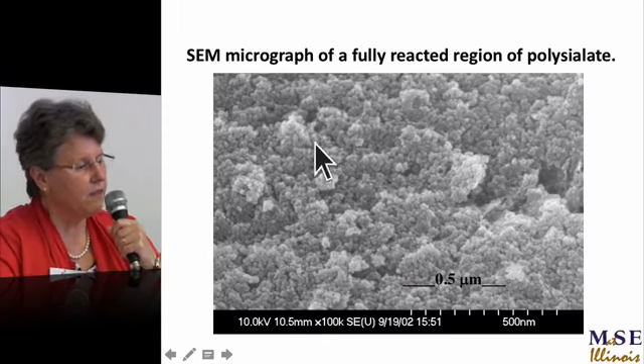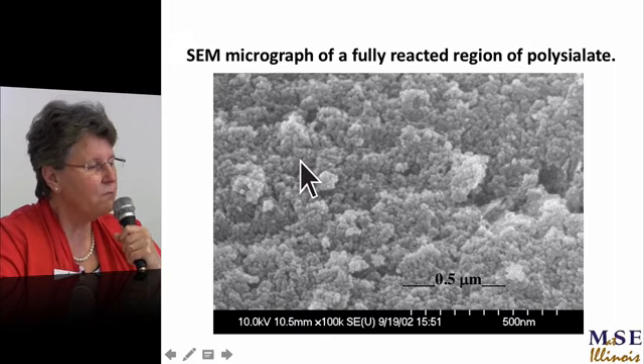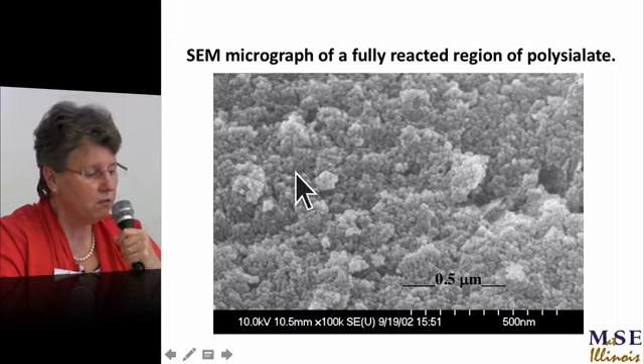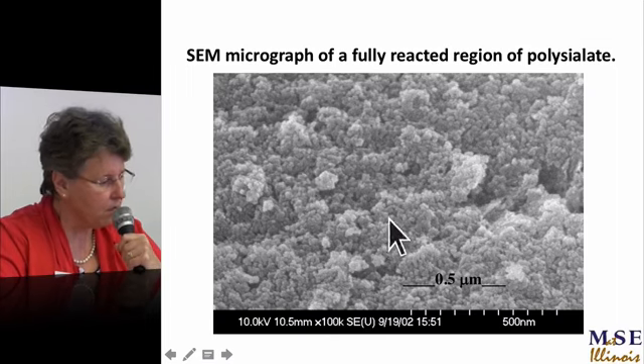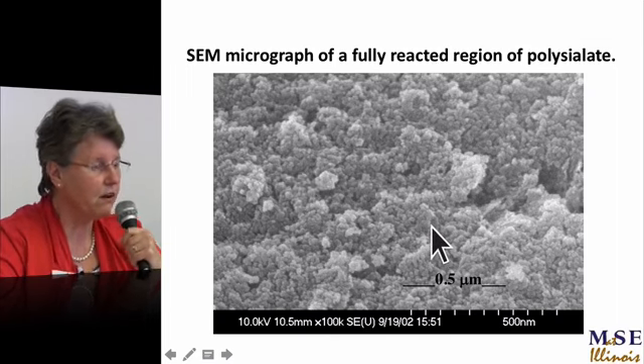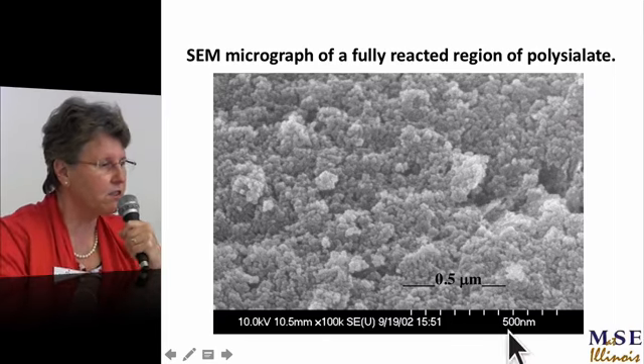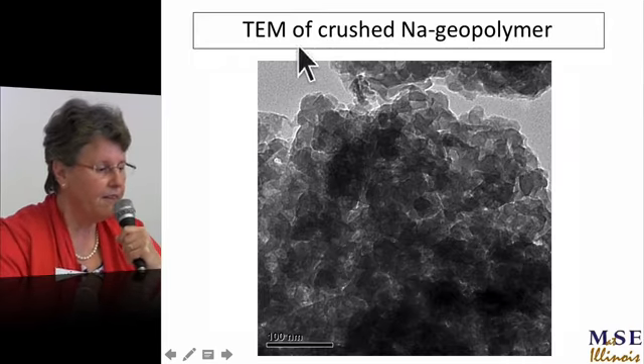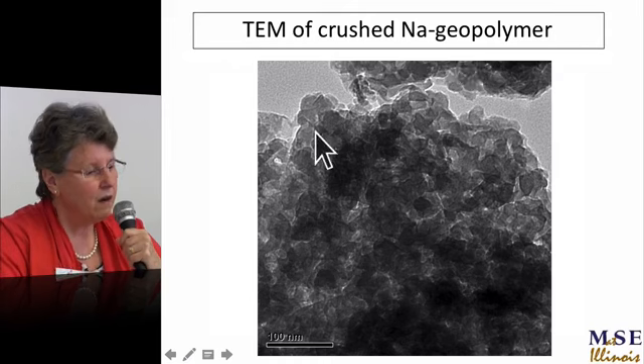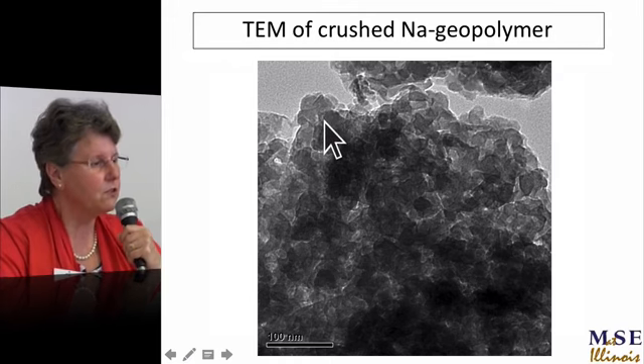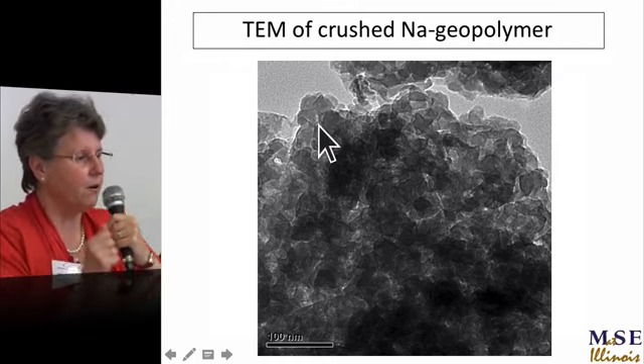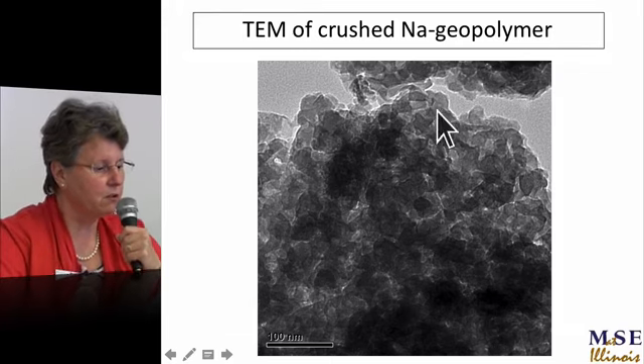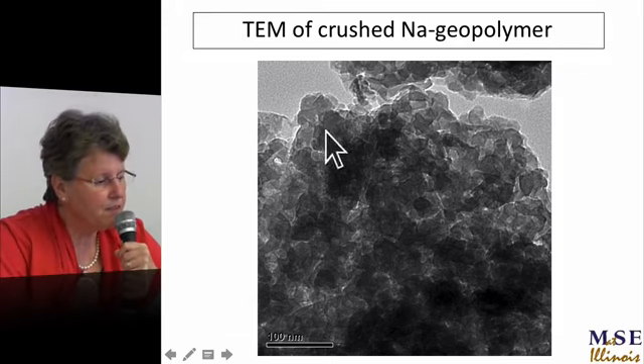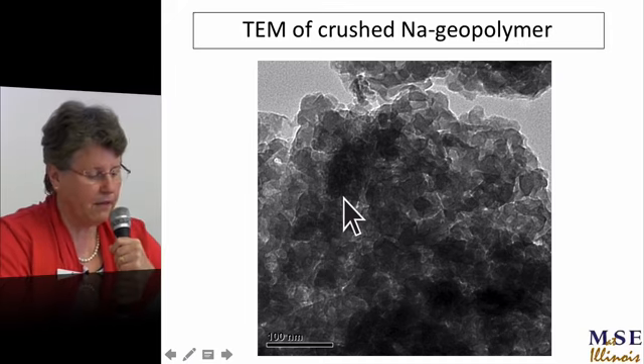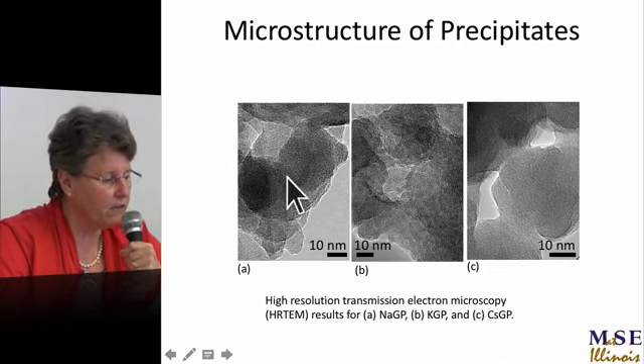And in the SEM, it's nanoparticulate and nanoporous. So they look like cauliflower to me, you know, a pretty weird structure. I mean, I teach TEM. I never saw such a crazy structure. And then in the TEM, well, if you just make it by crushing it and dispersing it on a grid, you get little nanoprecipitates. Little precipitates like pancakes that fall out.